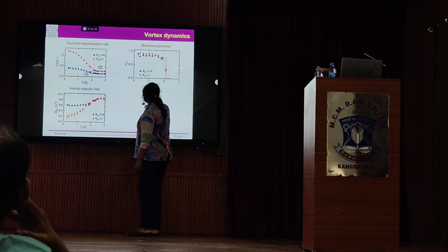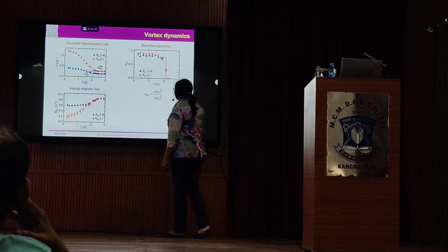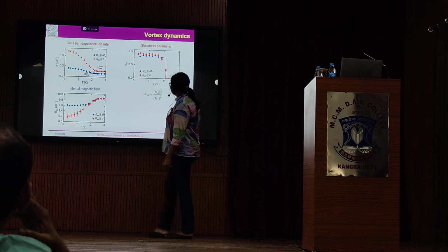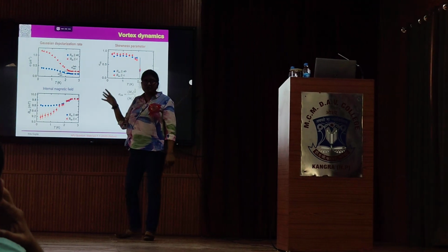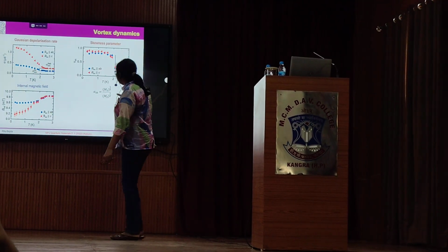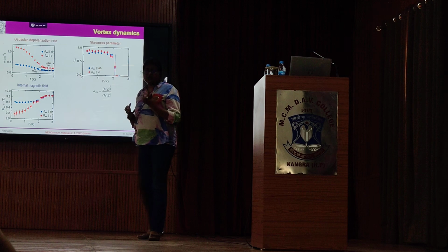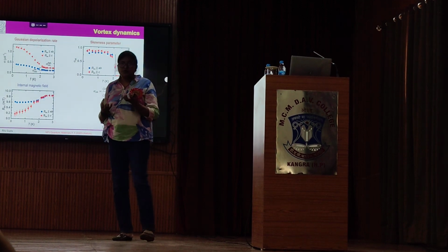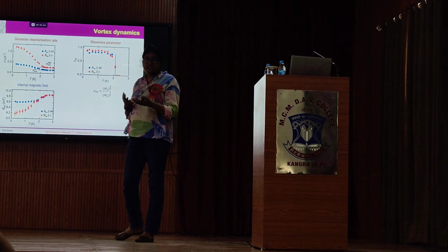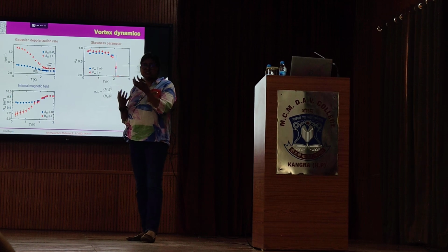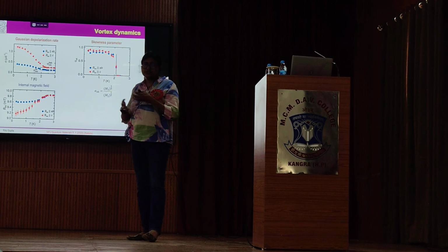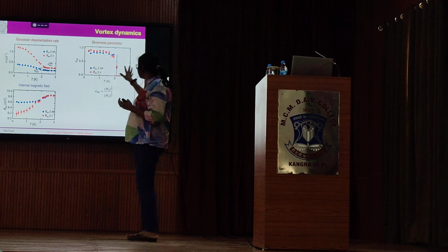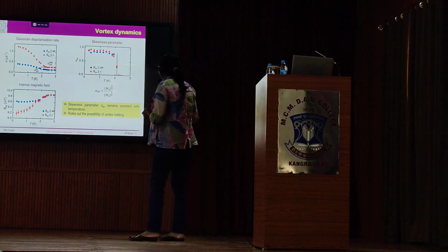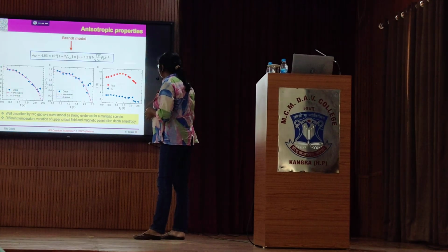And also one of the parameters is the skewness parameter. If this is greater than 1 or close to 1, that means your vortices are very rigid inside your material, and if this is less than 1, that means your vortices are not stable, they are flowing inside your material. Okay, so this is one piece of information given by the skewness parameter.